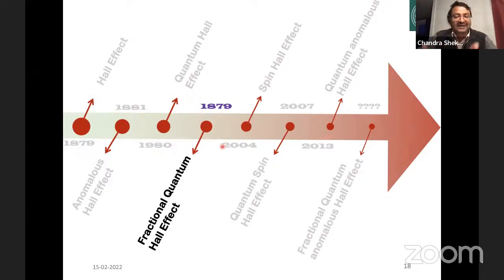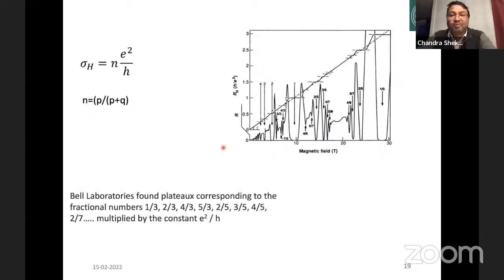Depending on the quality of the material, if you have an ultra-pure sample of the same material, then we can see some more steps in between. When we see such extra steps inside, we call it the fractional quantum Hall effect, because earlier we saw the steps in a straight line. Here is the bigger step, the first step, but in between we see many small steps. We can see 4, 3, 2, and 1 here.